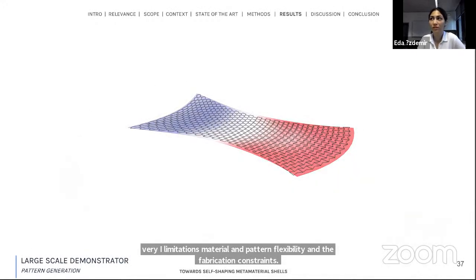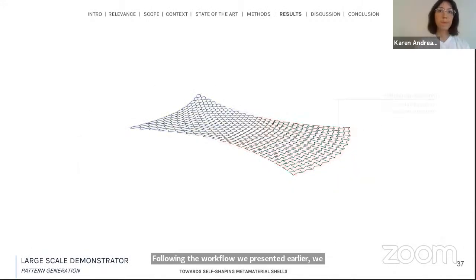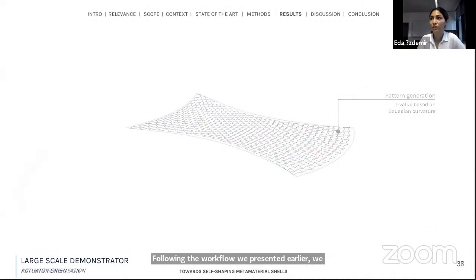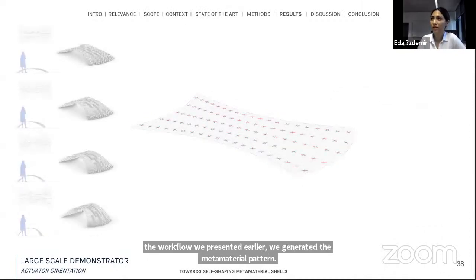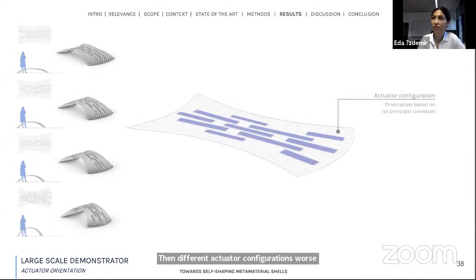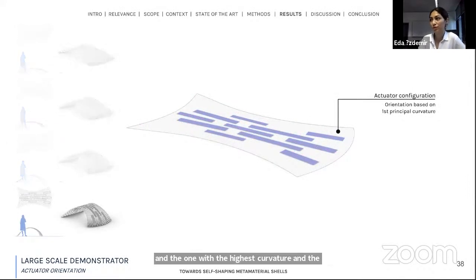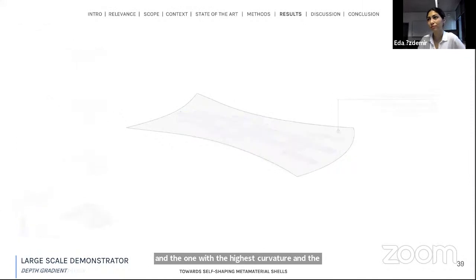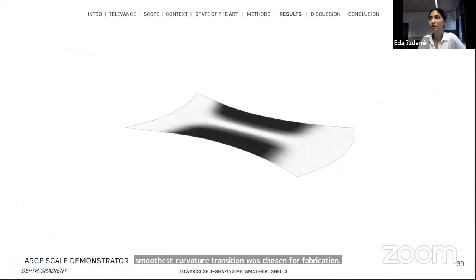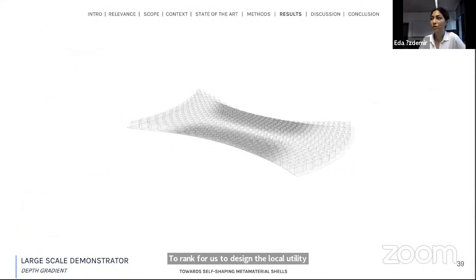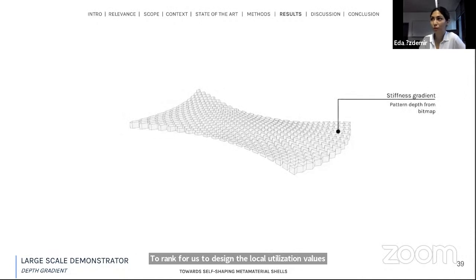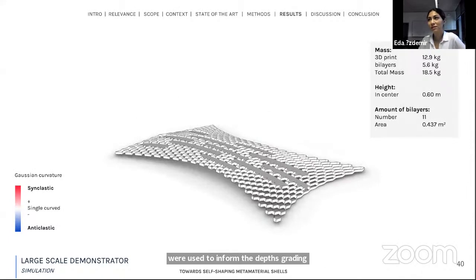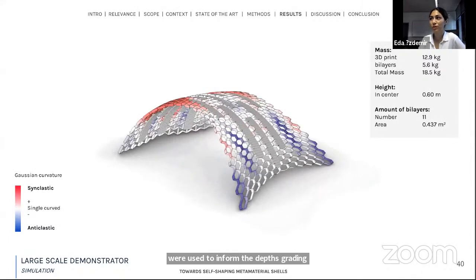Following the workflow we presented earlier, we generated the metamaterial pattern. Then different actuator configurations were simulated, and the one with the highest curvature and the smoothest curvature transition was chosen for fabrication. To reinforce the design, the local utilization values from the structural analysis of the chosen geometry were used to inform the depth gradient. Then, the simulation was used as a means to negotiate between the system parameters to find the ideal configuration that is closest to the design intent.